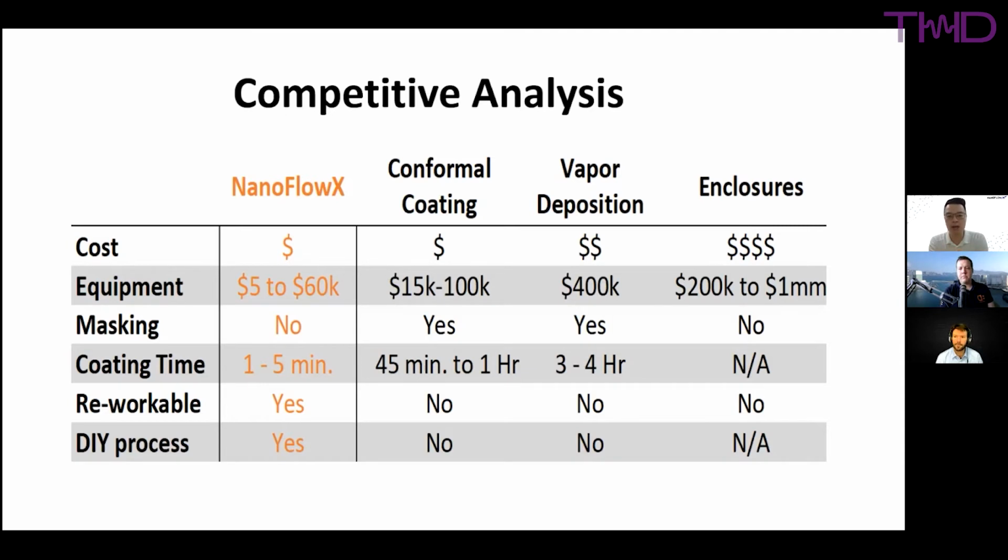But yeah, we are coating military Air Force rugged servers, and they were exposed to 300-hour salt fog while running. And we coated the entire SSD hard drives, the NVIDIA GPU cards, all that, and had zero effect. They were running a Parylene product, and the Parylene product would fail after 100 hours. And it goes back to the same issue. Parylene can't coat the connections. Right. Can't coat the connections, so they would fail very quickly.